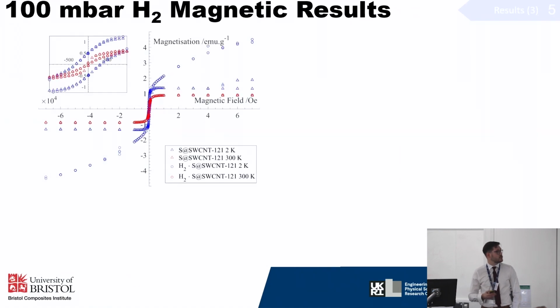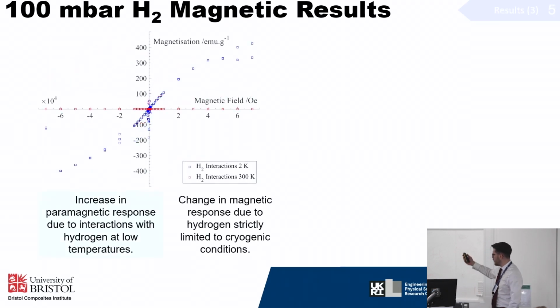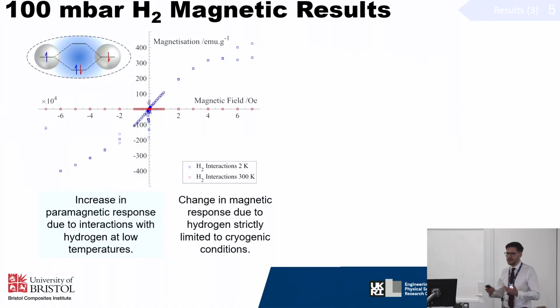But how does hydrogen change these properties? This is actually something that's really interesting. If we look at the interactions with hydrogen, we can see this increase in the paramagnetism. Why is this? If we subtract one from the other, we can actually see at low temperatures it is pretty much purely paramagnetic, and is limited only to the low temperature results. This is unusual because hydrogen has no unpaired electrons. You'd expect it to be a diamagnet rather than a paramagnet. So something clearly is happening in the system that is rather unexpected.